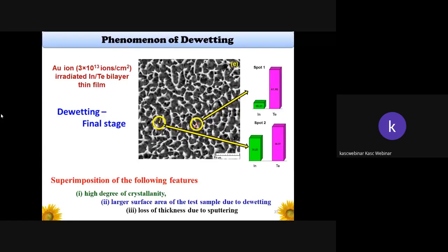Actually, this was subjected to 3 into 10 to the power of 13 ions per centimeter squared. We can say that the superposition of three different parameters, the high degree of crystallinity after the impact of higher doses, and the larger surface area, nothing but the higher porosity of the sample due to dewetting, and the loss of thickness as a certain amount of material gets ejected from the surface of the material, is also helpful to fabricate the gas sensor.